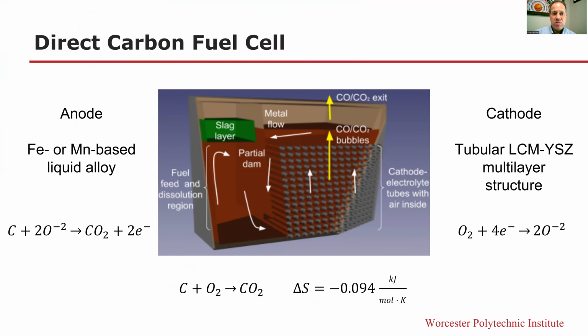So moving on, the direct carbon fuel cell solves a challenging problem of how do you get solid carbon to react with a solid electrolyte in a fuel cell. So here we dissolve that carbon in a liquid metal, such as an iron or a manganese-based liquid metal alloy. We have that dissolved carbon then react at the surface of a cathode electrolyte tube with air inside. So we're able to capture a very large fraction of the oxidation energy of the carbon in the potential across that electrolyte tube. So the entropy of the carbon combustion reaction is very low. So these direct carbon fuel cells have potential efficiency, theoretical efficiency, very close to 100%. So we'll see how close we can get to that here.